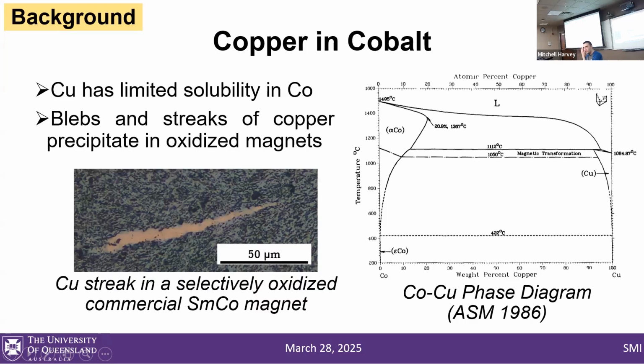I'm skipping ahead a little bit to show you a brief result. When we do this selective oxidation process, once all the other stabilizing elements—the samarium and zirconium that help stabilize the cobalt or the copper in the alloy—are removed by oxidizing them, you actually get these blebs and streaks of copper that precipitate in the oxidized magnets. So we're hoping we can somehow leverage this to separate the copper and the cobalt.